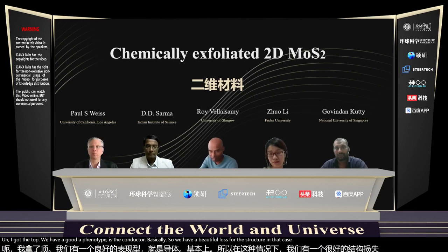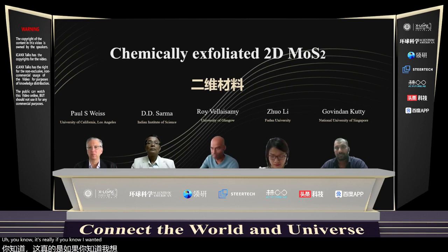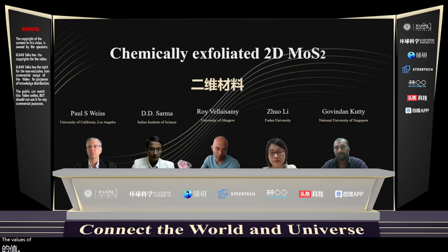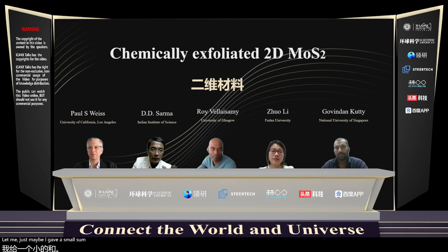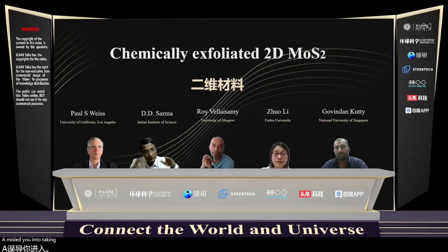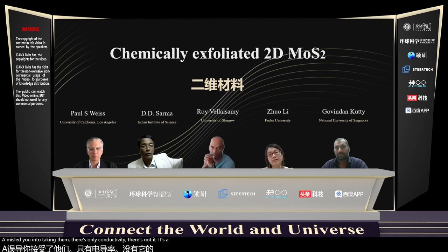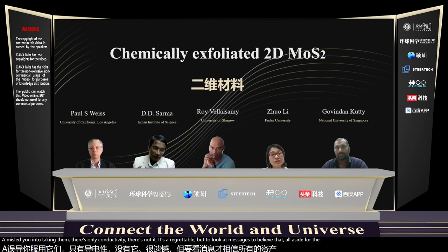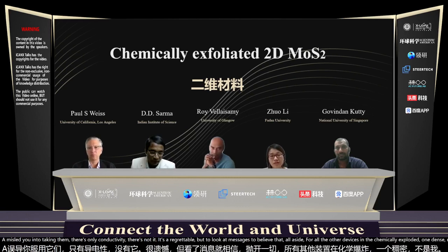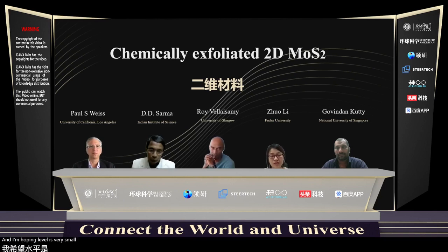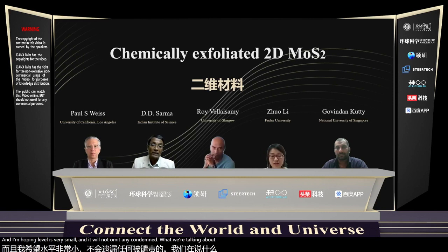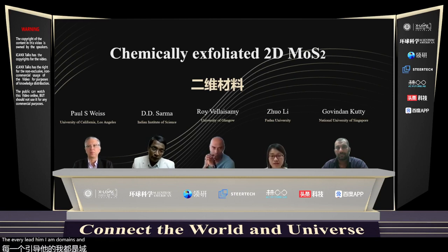In that case, if you have ionic transport, you will not get any workable device with the right switch-on values and so on. So how are we going to solve this issue? Maybe I misled you into thinking that there's ionic conductivity. There's none, except when we are talking about supercapacitors, etc.; leave that aside. For all the other devices and the chemically exfoliated one, there's no ionic conductivity. The ion doping level is very small, and we're not talking about ionic conductivity. What we are talking about is that every lithium ion donates an electron into the system, and the conductivity enhancement is due to those doped electrons.